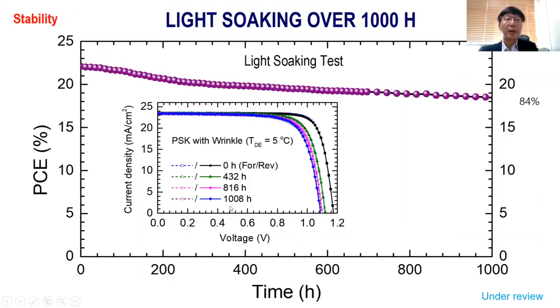And then we also tested the long-term stability, which is a light soaking test over 1,000 hours, and we found that after 1,000 hours, about 84% of the initial efficiency remained.